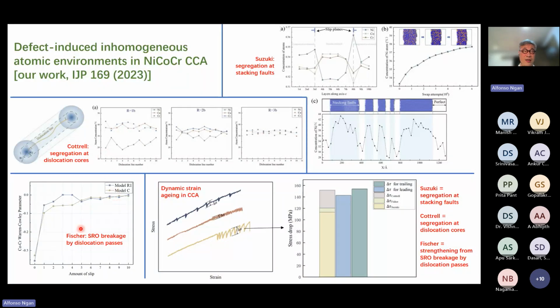We may also have the so-called Fischer strengthening effect, which is when a dislocation moves it may destroy the short-range ordering. So by breaking the short-range ordering, there will be some resistance arising from that breakage, and that would cause certain strengthening as well. So some of these CCAs would exhibit dynamic strain aging. So during deformation, especially at lower deformation rate, there will be stress jumps. And the stress jumps are on the order of a few dozen or about 100 megapascal.